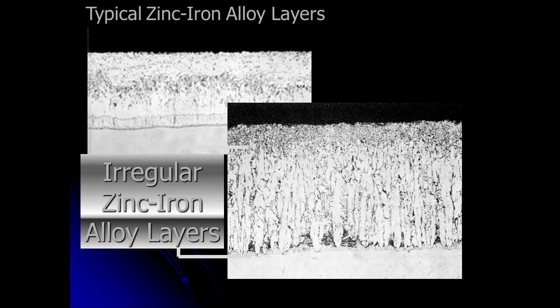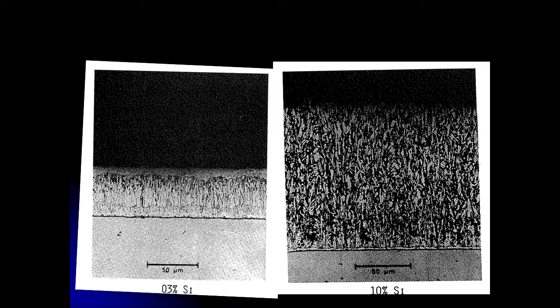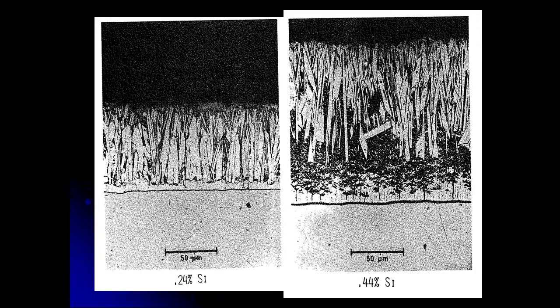This is your typical iron zinc alloy layer. It's not a very good picture. What happens when you have reactive steel, you have these irregular iron zinc alloy layers and these columnar crystals that are growing more vertically. So at 0.03% silicon, you can see the columnar crystals. At 10, look at the columnar crystals at 0.24, 0.44. How much adhesion do you think you have here? You're not going to have a lot of adhesion here.